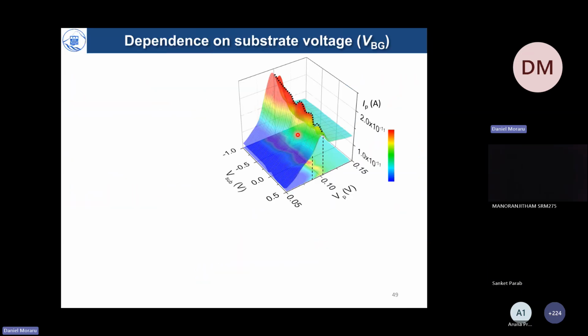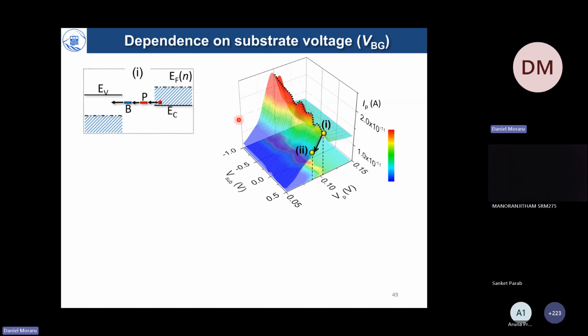Now, this sharply enhanced current peak is illustrated here as a function of VP, the bias applied to the P side, and also V sub. We can use the substrate voltage as a gate. So we can monitor what happens if you align two such energy levels, one induced by a phosphorus quantum dot and one by a boron quantum dot, in a sort of resonance.